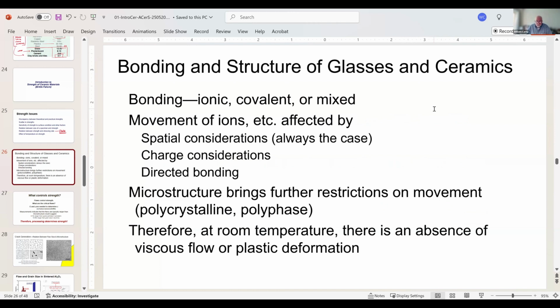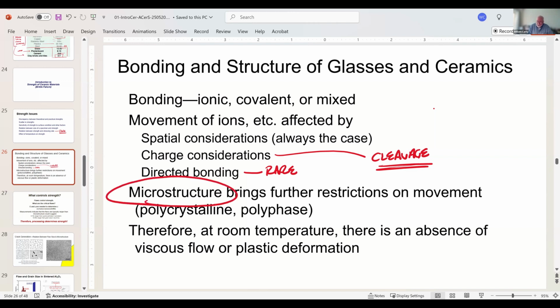That's common. We mentioned bonding before, and in glasses and ceramics, this becomes important for us for strength. We have ionic or covalent or a mixture of both, almost always a mixture. Ions, basically, they don't move very much, okay? Directional bonding is also relatively rare, except when you get into composites. Charge considerations, this mainly deals with something called cleavage, which is where you would fracture along a crystallographic orientation. Then there has to be a balanced charge to make that happen. But the biggest issue we have is this: microstructure dictates everything in terms of the strength of these materials for the most part. Okay, because if my microstructures are irregular, having big grains and small grains, for example, or pockets where there are no grains, where I have a hole, that increases the likelihood of failure or becoming what's called a critical flaw. And at room temperature, there's no viscous flow typically, no plastic deformation. Okay, so the consequence is everything is brittle.